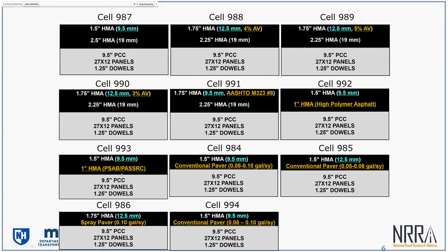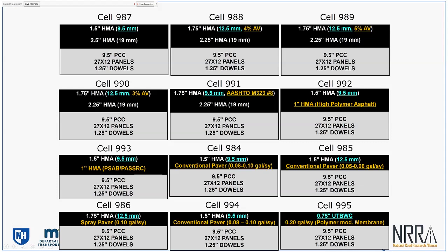And also in case of 986, that one is actually placed with a spray paver doing a thin bonded overlay, or a bonded overlay, with a high shot rate on your tack coat emulsion of 1/10 of a gallon per square yard, versus 984, more traditional shot rate of 0.08, 985 a lower than traditional rate, so 0.05, and these are diluted rates, so the actual emulsion amount is even lower, but this is with dilution. And then lastly, cell 995, this one is a true ultra thin bonded wear course that has a very high tack coat rate of 0.2 gallons per square yard. And in that case, actually, the tack coat is also polymer modified emulsion, so emulsion made with polymer modified binder. So those are different cells, and that obviously is going to help us populate all the information that we need towards developing these decision trees.